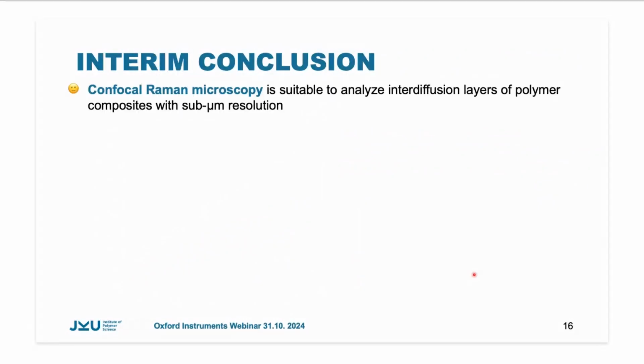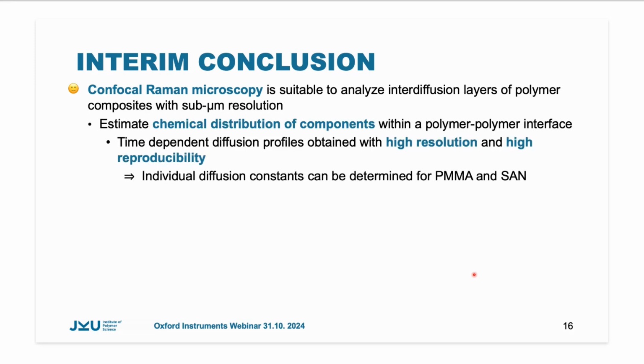I can give you a first interim conclusion. I hope I could show you that confocal Raman microscopy is a suitable tool to analyze the interdiffusion layer of polymer composites with sub-micron resolution. We could estimate the chemical distribution of the compounds along the polymer-polymer interface, which allows us to elucidate time-dependent diffusion profiles with a very high resolution and a very high reproducibility. And we could determine different interdiffusion constants for the different polymers.